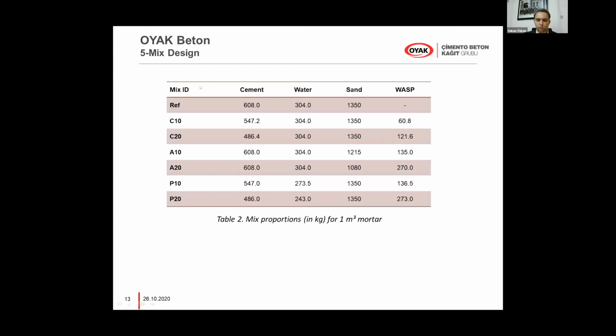And here we can talk about our mix design. Three incorporating methods were used, and their effects on the durability properties of cement mortars were researched in this study by determining the void content, sorptivity, and non-steady state chloride migration tests. There are 2 different replacement ratios, 10 and 20. First of all, we performed cement replacement, then fine aggregate replacement, then paste replacement. In total, we have 7 different mix designs. Here are the ingredients of the reference mix design for 1 cubic meter.